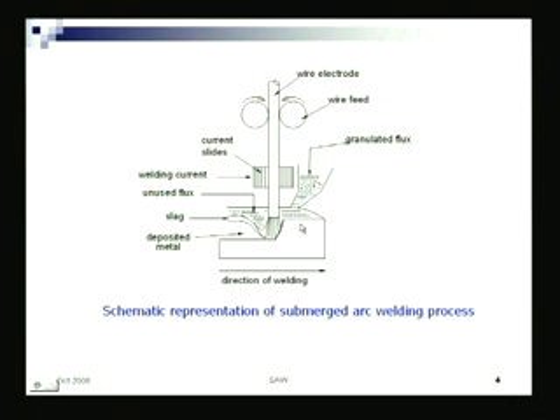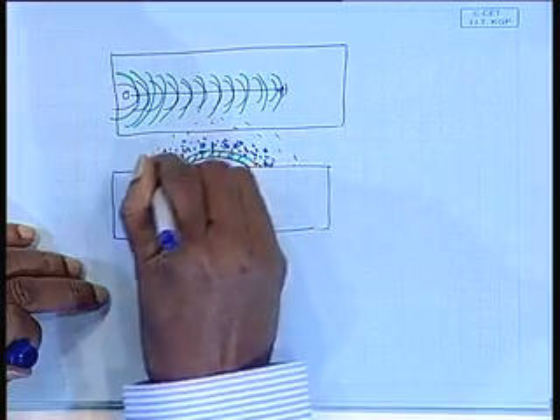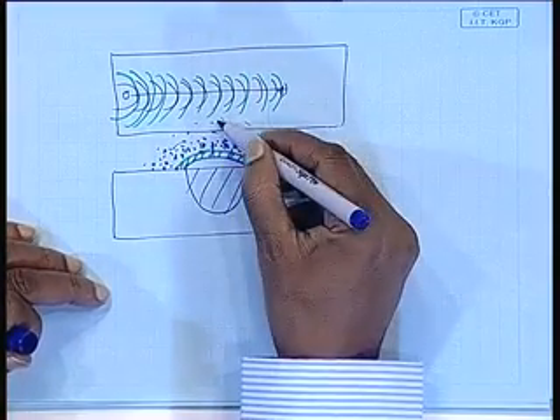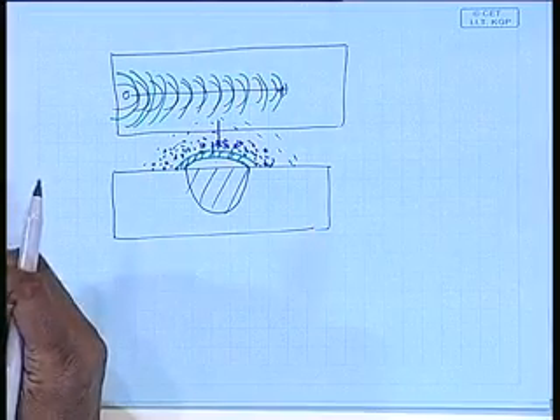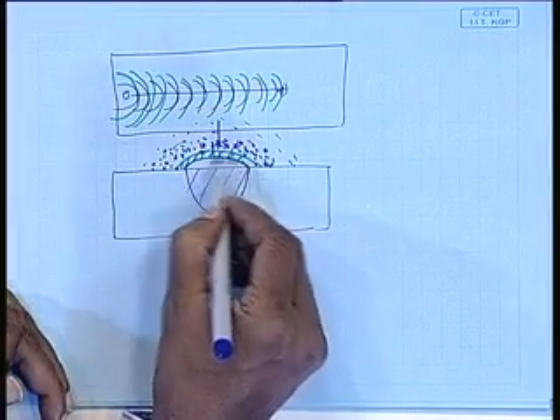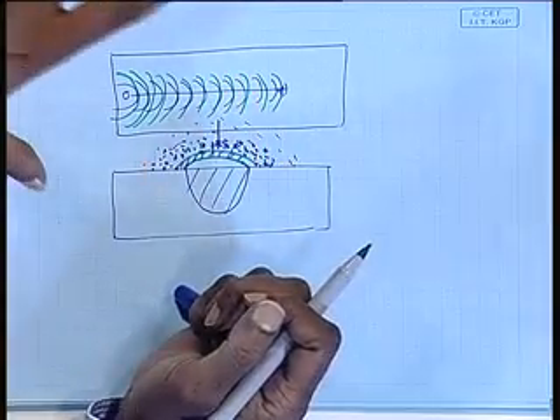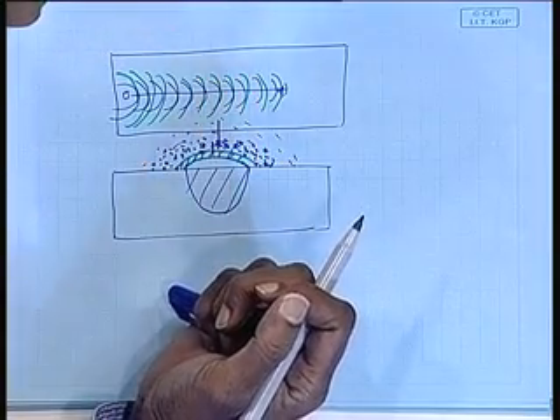That means, regarding the hopper height, if the hopper height is much above, too much flux will fall, so if the flux layer is very huge, that is also not good, because it will add weight to the molten metal, causing contamination of the flux. The molten slag should float up, but if it is loaded with too much unburned flux, it will add pressure, so the molten slag will not be able to come up, giving rise to a defect called slag inclusion.